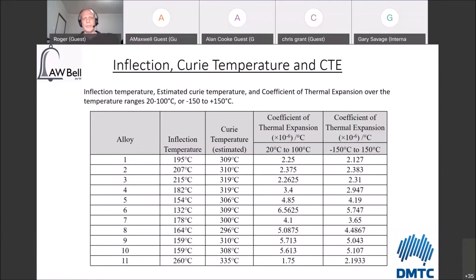We looked at this a little bit further, and did move towards a second set of experiments. But one of the things I did want to point out here was these two results. Now, these were from alloys that were not the best alloys in terms of coefficient of thermal expansion, and possibly not the best in terms of some of the issues we came up against with hot tearing. But what these do have is the same coefficient of thermal expansion as borosilicate glass, in the case of this one around about 3, and single crystal sapphire.